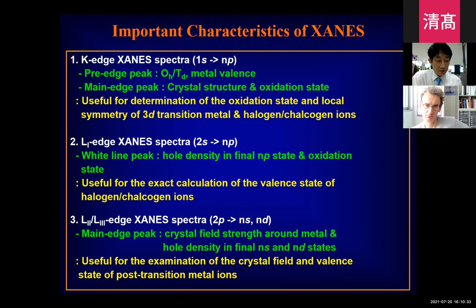In the case of the L2 and L3-edge XANES spectra, the excited core level is 2p at those edges. So in the XANES spectra, we can get spectral features corresponding to the transition from 2p to ns or nd. From that, we can get information about the crystal field strength and the hole density of the final ns and nd states.